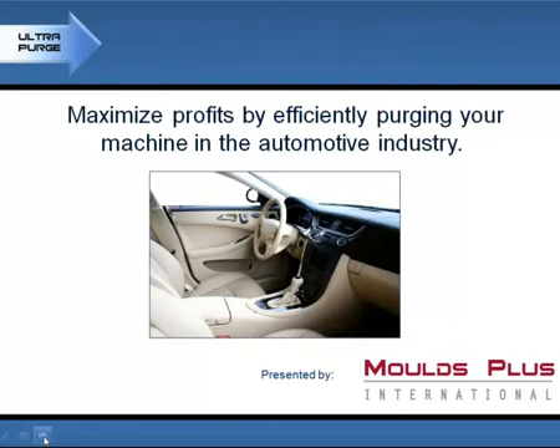It's not something that you can basically chemically dissolve. What we are able to do is soften, with our chemical ingredients, the carbon a little bit, but what we call the amorphous carbon. The amorphous carbon is normally much softer than the crystalline carbon, which is much harder. The crystalline carbon is normally formed in the compression zone of the screw. And normally we are not able to clean the crystalline carbon, but no other material is able to clean crystalline carbon. It's too hard to be actually cleaned. Normally only a mechanical cleaning can solve that. But definitely the UltraPurge is sufficient for removing what we call the amorphous carbon. Again, it's normally formed in the feeding zone of the screw or in the hot runner system or in the manifold.